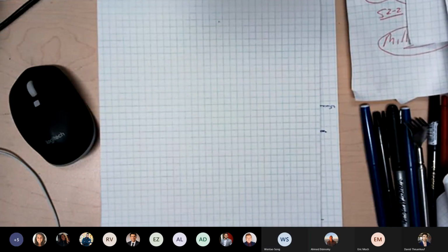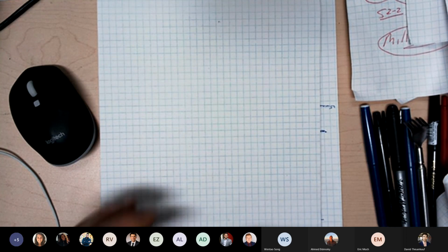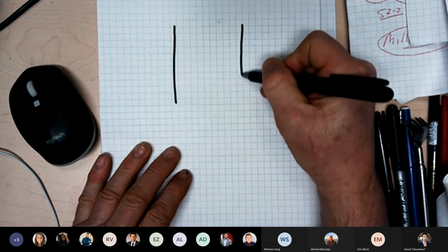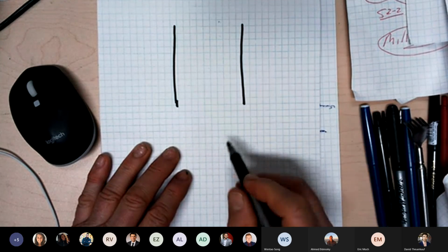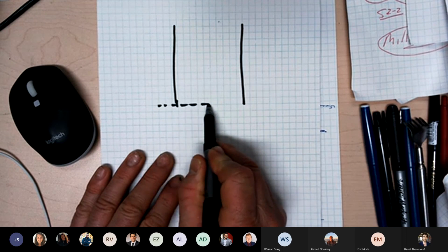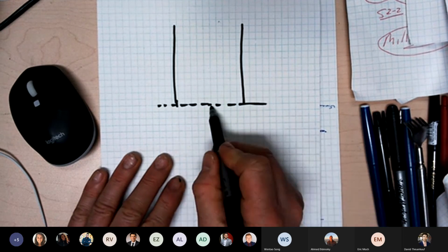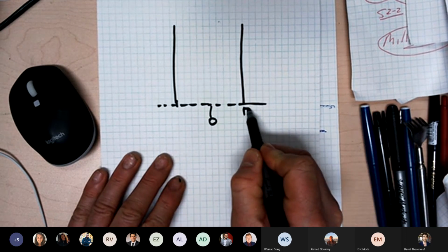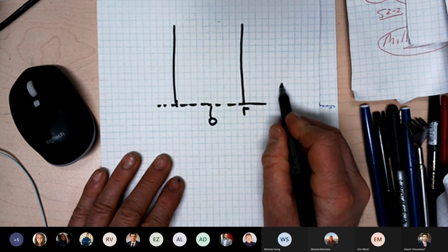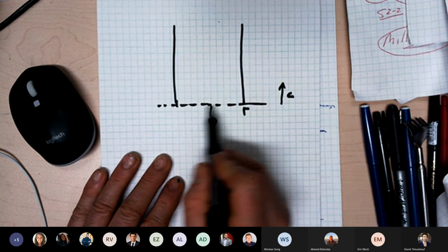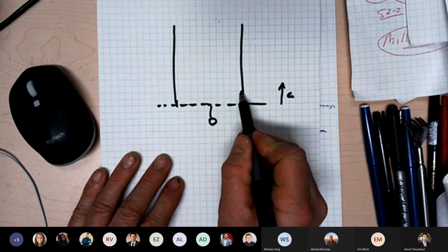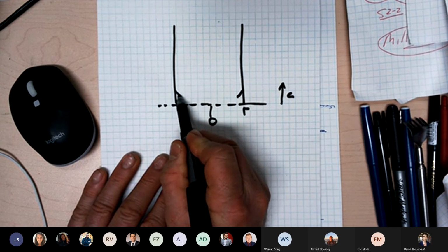So let's understand why the concentration gradient in the plane case is 0 at the center. So here we are with a plane, and we have 0 at the center and r at the surface. And we'll just plot the concentration in this direction. So we start with the concentration 0 everywhere, and we start putting lithium in at the surfaces, right?